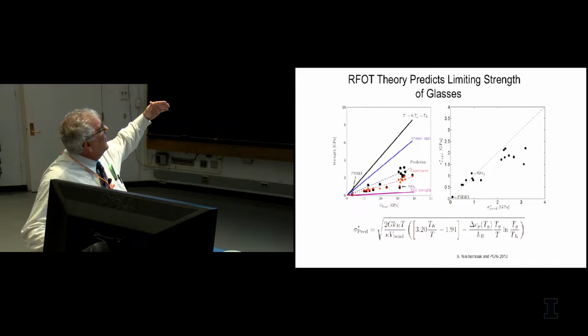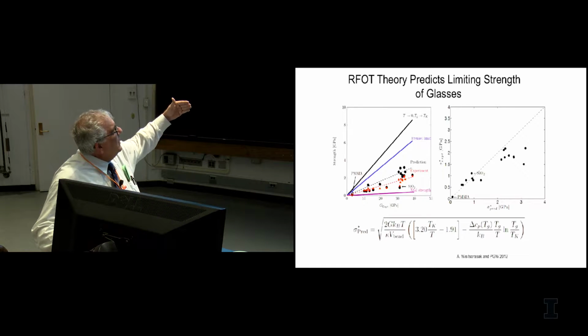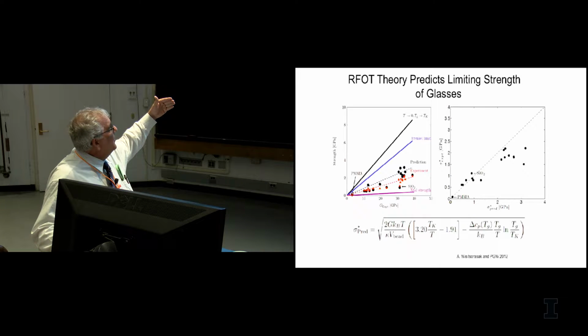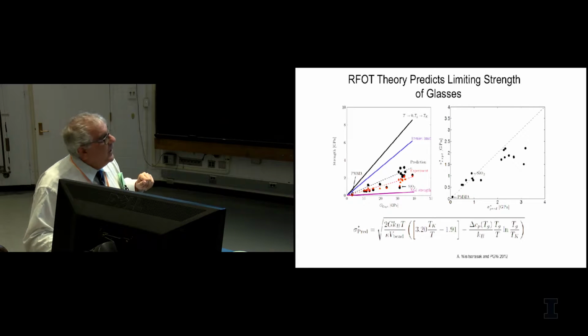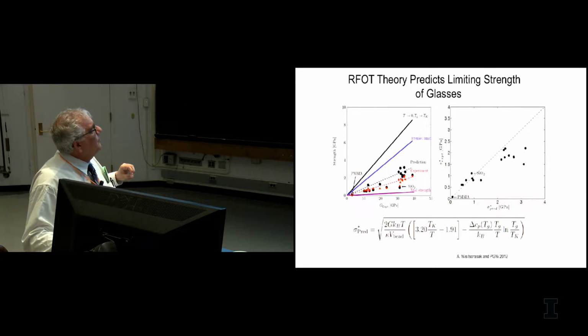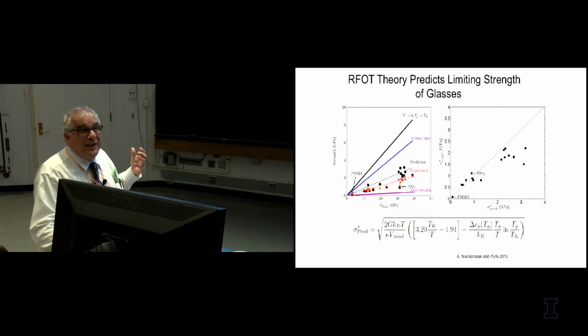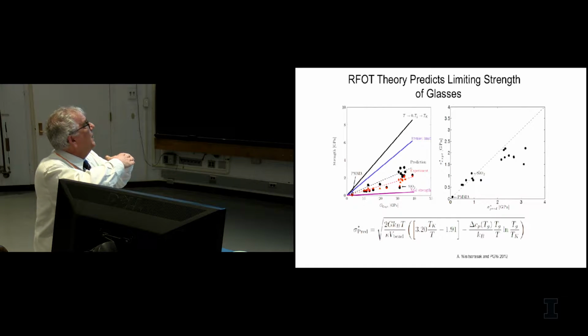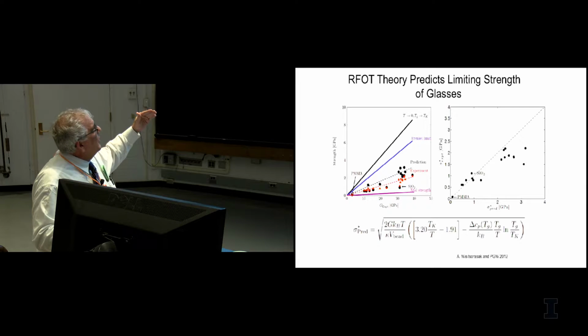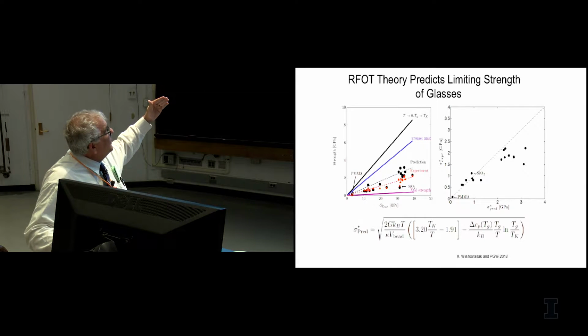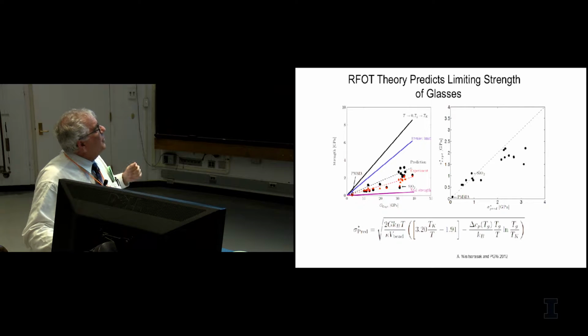First of all, the strength in general comes out to be proportional to the elastic modulus itself. It also involves a temperature, and then it involves some corrections that depend on how much stored energy you have and the entropies. Well, first of all, the amazing thing about glass that's been known for a long time is glass actually is very strong. In the 20s, I think, or maybe the 10s, Frenkel calculated the limit of strength of a material by rolling one lattice over another, and he got a very large number. It's also proportional to the elastic modulus, and the strength is shown in that purple curve as the Frenkel limit.